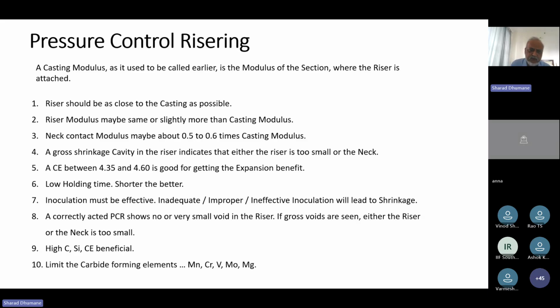So inoculation must be effective not only for avoiding your machining problems and other problems, but most importantly, for your graphite expansion. If your inoculation is ineffective, your graphite precipitation will be inadequate, and then it will not compensate your shrinkage fully, and you run a risk of shrinkage defect. So that is why inoculation is important. And since inoculation is related to melt quality, again we are coming back. Holding time, inoculation. These are the factors which decide your melt quality, and this impacts your shrinkage defect. So now we are slowly understanding how melt quality affects your shrinkage defects. Correct?